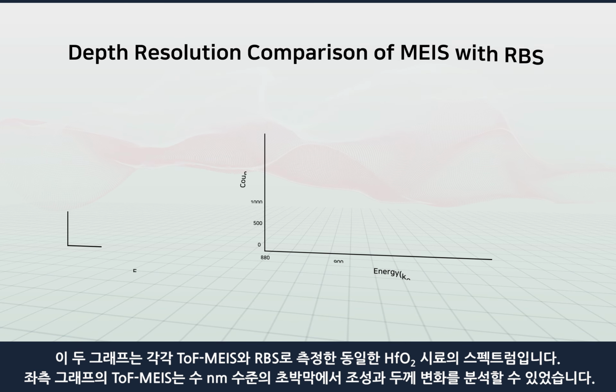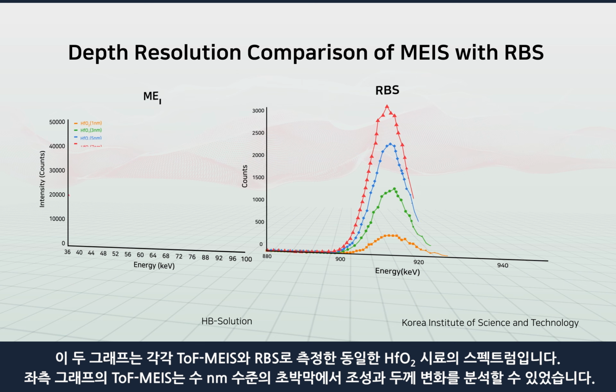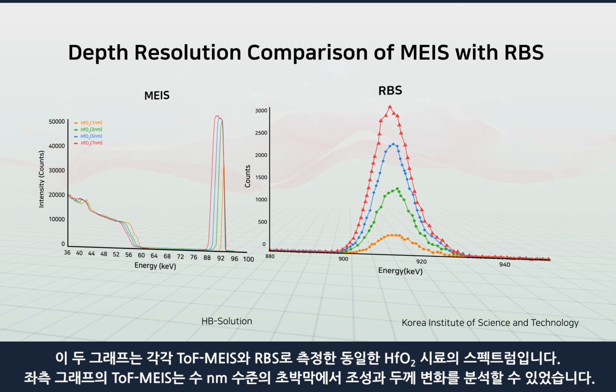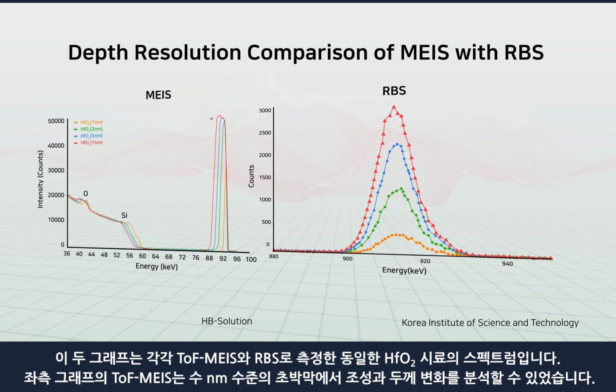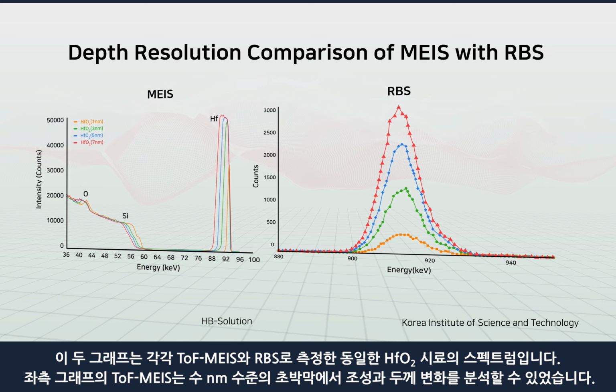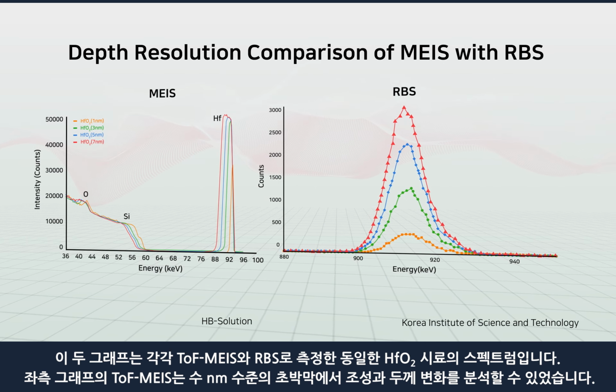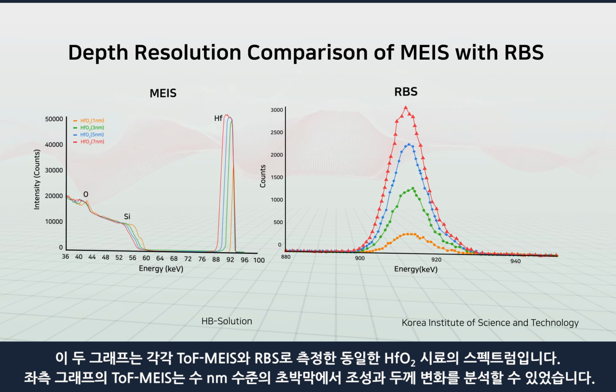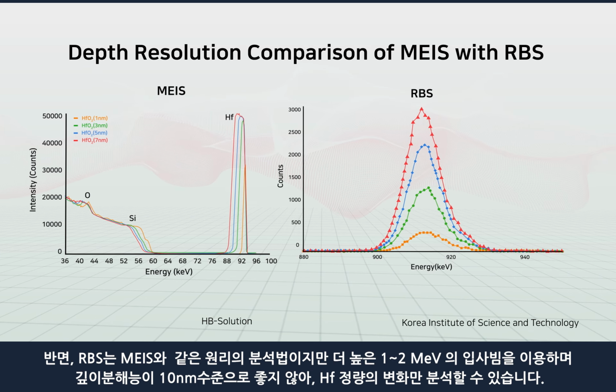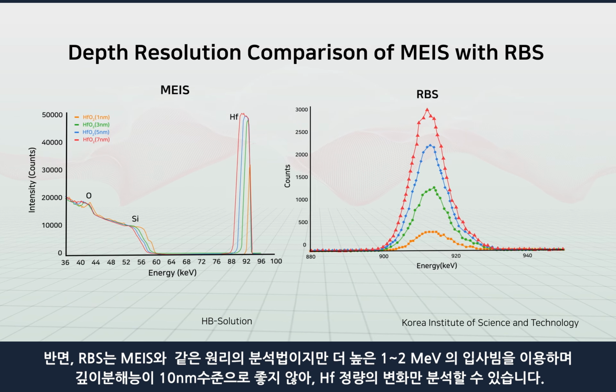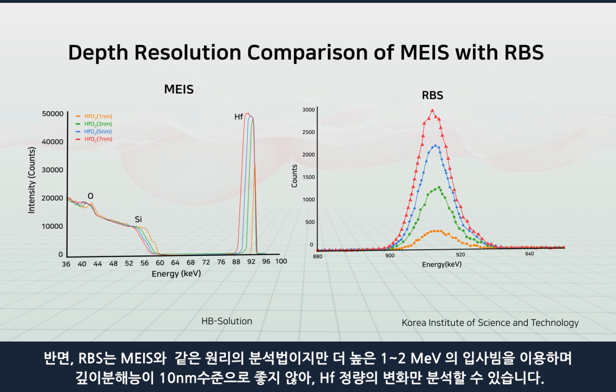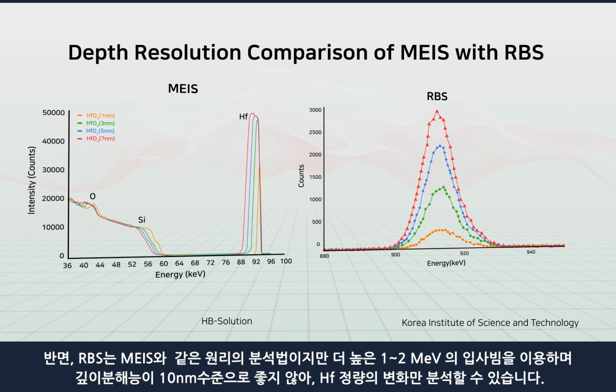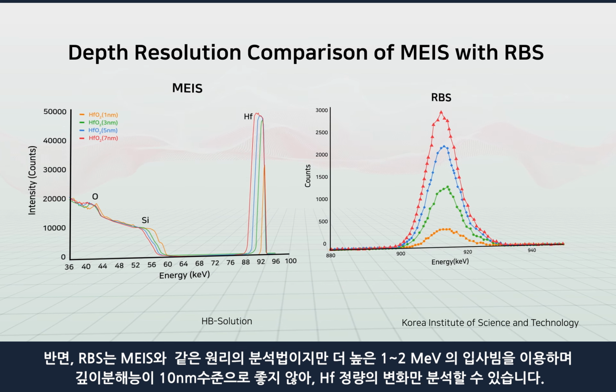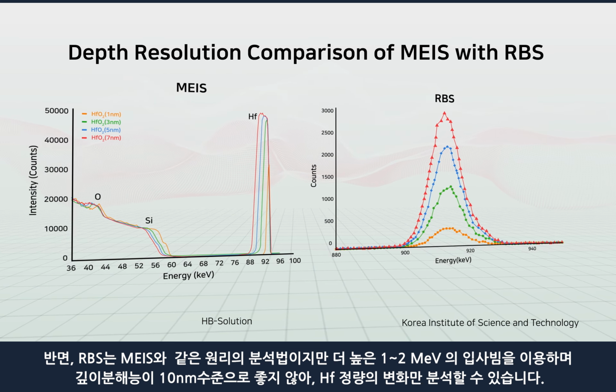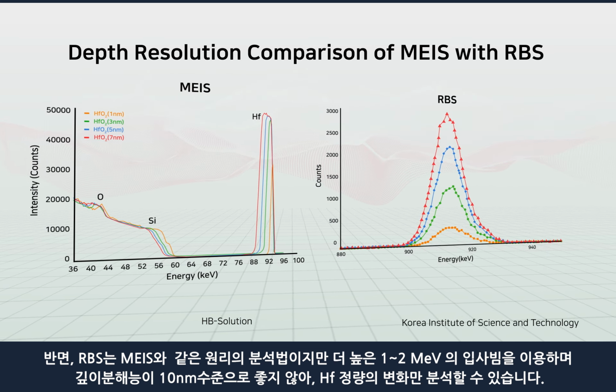These two graphs show the results of analyzing the same hafnium oxide sample with TOF-MEIS and RBS, respectively. The TOF-MEIS, as shown in the graph on the left, was able to analyze the composition and thickness changes in ultrathin films of a few nanometers. However, RBS uses an incident beam of 1 to 2 mega electron volts on the same principle as MEIS and has a depth resolution of 10 nanometers or more. Therefore, only changes in hafnium quantification could be analyzed.